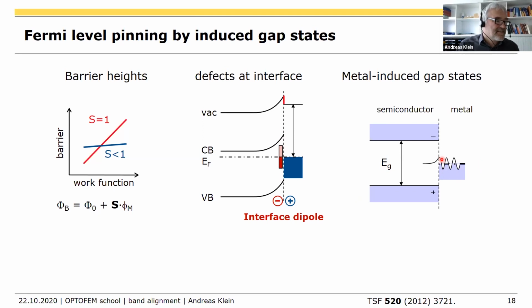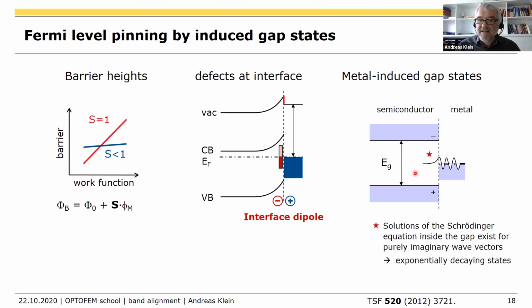Now, if you did a quantum mechanics course in your studies, you should probably have done the tunneling effect. When you have a tunneling effect, you know that the wave function in the semiconductor, if you have a barrier here, and this is a barrier for the electrons, then you do not have oscillating states in this material, but exponentially decaying states. The Schrödinger equation in the band gap of a semiconductor has solutions, but there are no electronic states, because these solutions cannot be normalized. They cannot be normalized because the k vector is imaginary. So you have exponent minus ikx, and if k is imaginary, you simply have an exponentially decaying function.